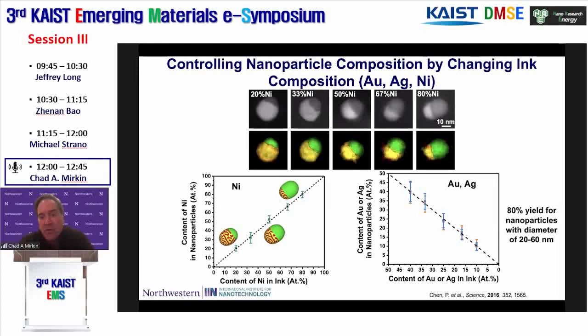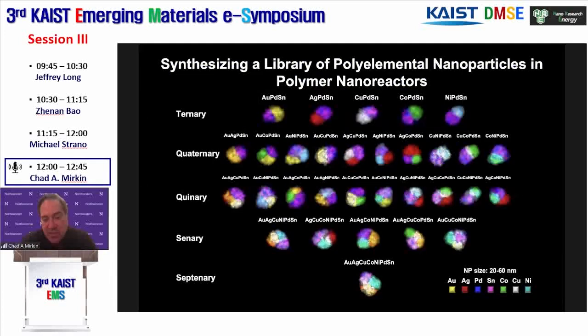If I take different salts, gold, silver, and nickel, for example, mix them up in the polymer, put them on the tips, you can see what you put in the polymer ends up in the particle. So here we've intentionally, systematically varied the nickel content in a 3-component particle from 20% to 80% as we go from left to right. The green is the nickel. The gold and silver is intentionally kept at a 1-to-1 ratio just to show the control that we have. So we're pretty much convinced in these types of reactions, what you put in the polymer reactor ends up in the particle. If that didn't convince you, this should.